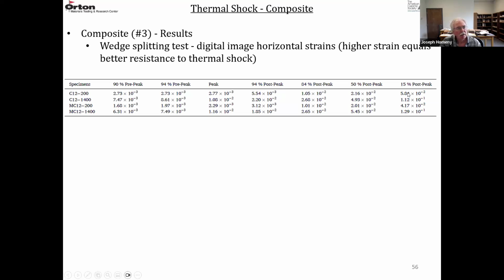And then there's a lot less strain. This is 5.84 times 10 to the minus 2, 4.17 times 10 to the minus 2. These are for the 200 degree C cures. So coking the material at high temperatures increases the amount of strain to failure.